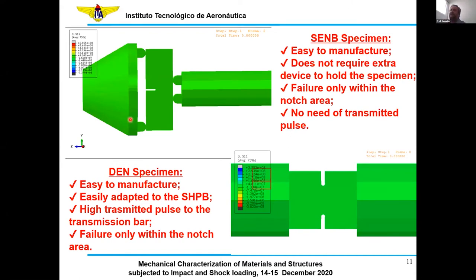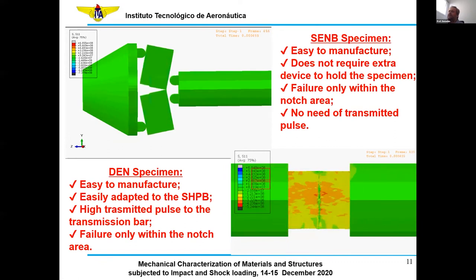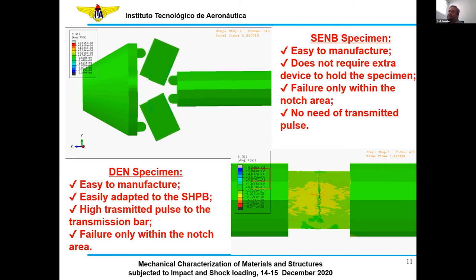The definition of the specimen configuration and dimensions were based on simulation. I mean, some points here were addressed to define the configuration. The first one, as I mentioned before, is the stress concentration factor. We must have a very high stress concentration factor at the crack tip in order to ensure that we have propagation ahead of the crack tip. And the stress concentration in composite is not only dependent on the geometry, it also depends on the layup, right?